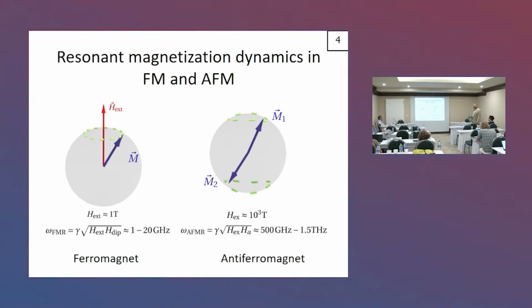And what can you do? You can apply the spin polarization perpendicular to the direction of magnetizations in the antiferromagnet. In that case, you can slightly tilt the antiparallel directions of magnetization. Can you tilt them strongly? No, because the force which makes them antiparallel is 1,000 Tesla. So you can probably get a tilt of 1 degree or a couple of degrees. But this is enough. If you do that, the tilted antiferromagnetic sublattices will start to rotate in this huge exchange field, and you will get frequencies of this rotation, Larmor frequencies, which are in the sub-terahertz or terahertz frequency range.